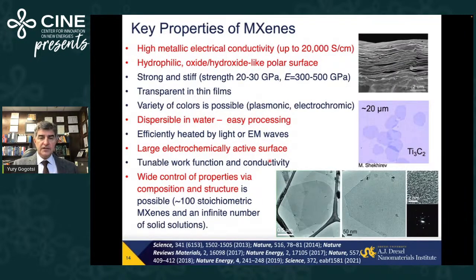Now, great to be able to have many new materials. There are quite a few already available to us. It's great to be able to produce them in quantities, but does anyone need them? People look for specific properties that other materials don't provide. And one of them is the high metallic electric conductivity of MXenes. If you take the single layer flakes, which look very much like flakes of graphene or molybdenum disulfide or other materials, they're single crystalline, as you can see from selected area diffraction and high resolution TEM.